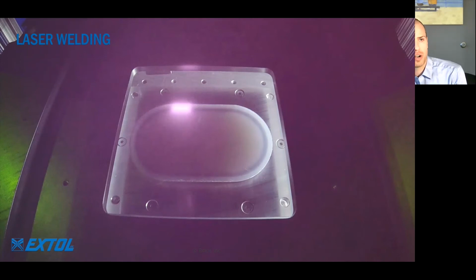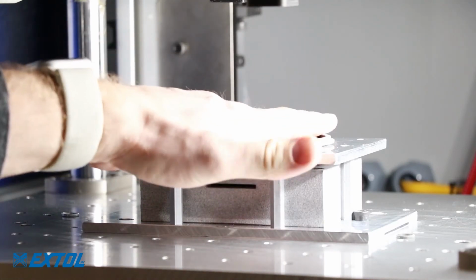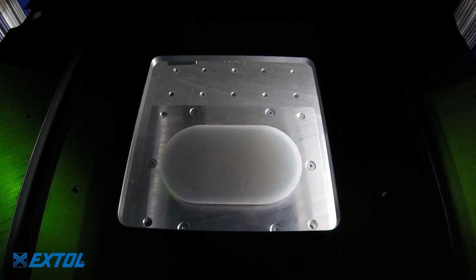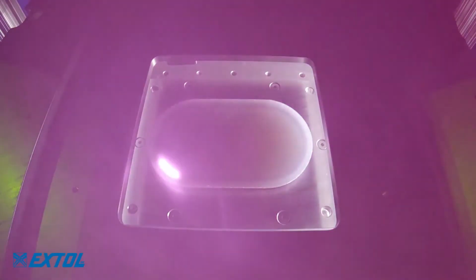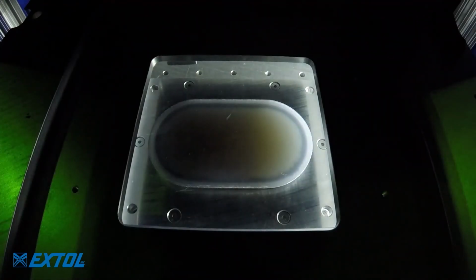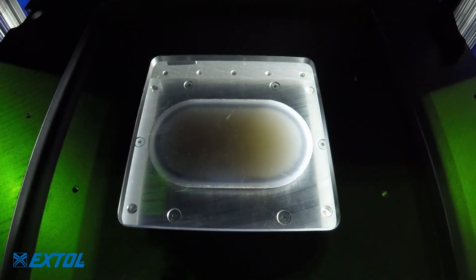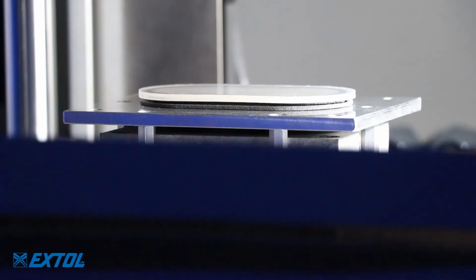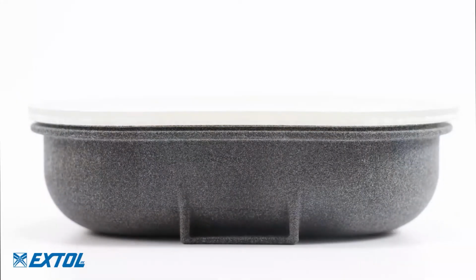Here's a video of the welding process for laser welding. Parts are put into the fixture, they're clamped together up against the glass. The laser quasi-simultaneously welds, which means it goes around multiple cycles and melts the extruded polypropylene sheet to the base polypropylene that's been 3D printed. The laser is actually passing through that upper translucent layer and absorbing into the bottom layer at the weld joint, and that's what's heating and melting the parts together.